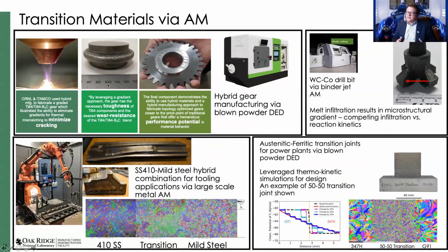I want to follow up by stating that one of the big areas as we do this is starting to look at hybrid structures and graded scenarios. So I gave you one example. Really the future to me in additive, for where we can enhance performance, is how you use these multi-material scenarios. For gears, we've shown scenarios where we made titanium alloy central portions of the gear, but then used a Ti64 B4C material, a composite material on the outside, drastically increasing the hardness and wear resistance of that gear. We've shown in tungsten carbide cobalt where we can look at infiltrants and infiltrate with either a nickel or steel, and you can start thinking about graded structures as we do this.